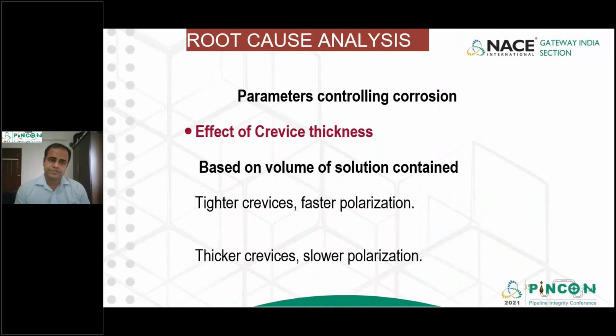Third thing that we have observed is the effect of crevice thickness. Now, I wonder how many of you are aware that a crevice, the tighter it is, the faster is the polarization, because I have already told you that the cathodic protection not only polarizes the pipeline, but also alkalizes the ground potentials, the groundwater potentials. So if we have a tighter crevice, the polarization is much faster, and a thicker crevice will have a lesser and slower polarization rate. Hence, the amount of solution which is expected to be contained in these crevices is driven by the tightness of the crevice.